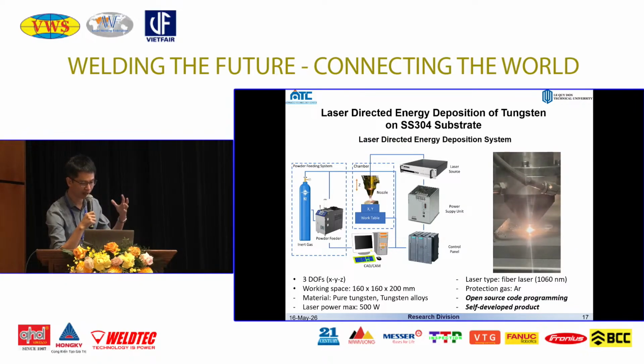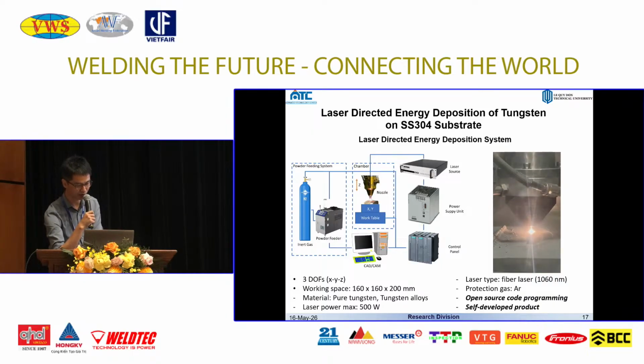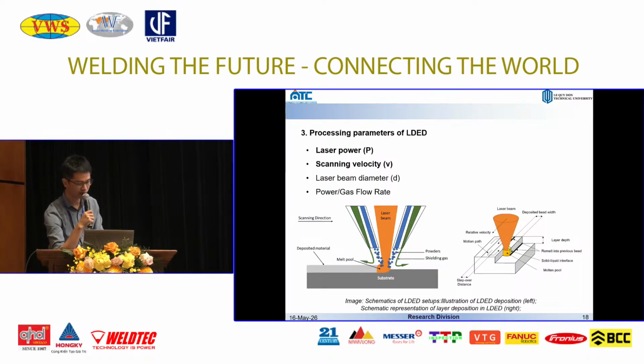We tried to conduct some pilot printing tests on tungsten using our system, as we saw before. Before doing the experiment, we determined some key parameters we need to control, like the laser power, scanning velocity, laser beam diameter, and powder gas flow rate. But in this very pilot experiment, we just focus on the laser power and the scanning velocity.